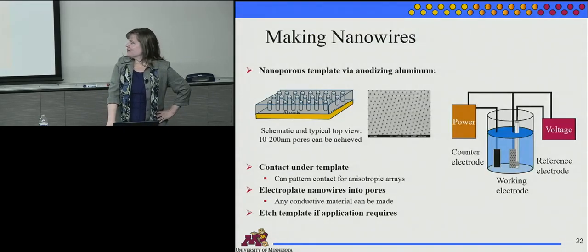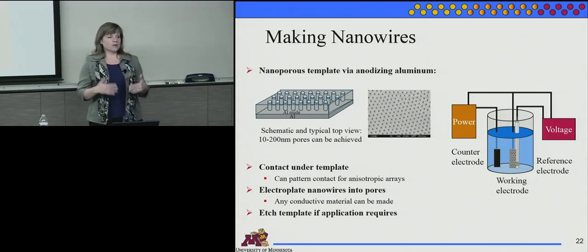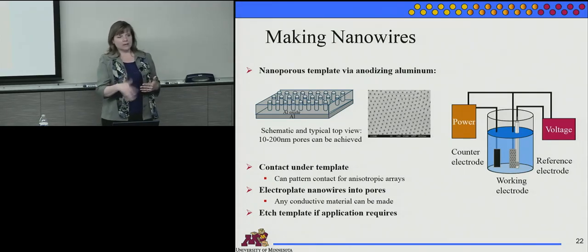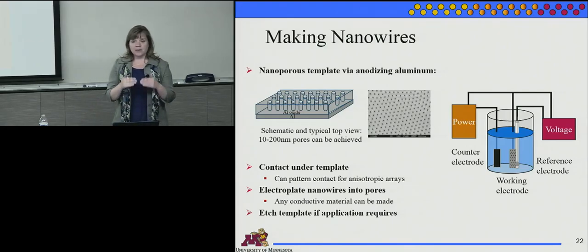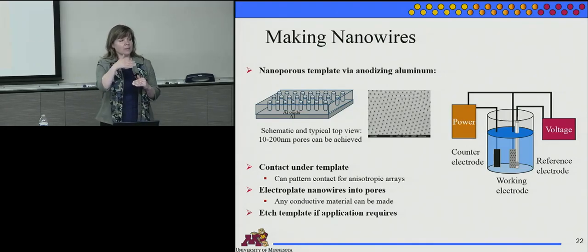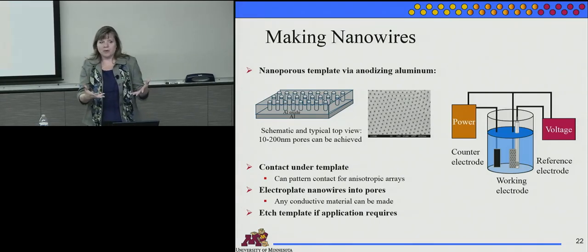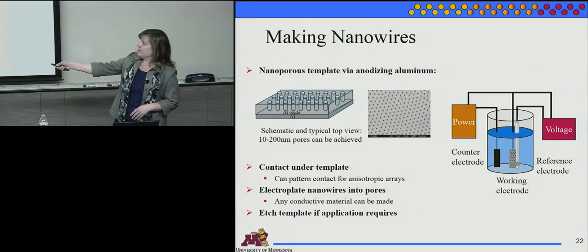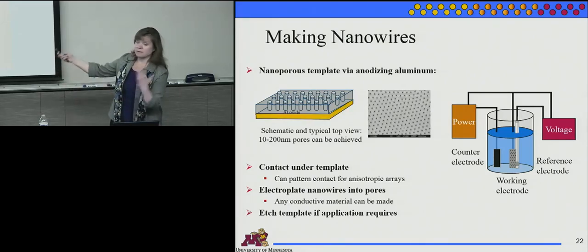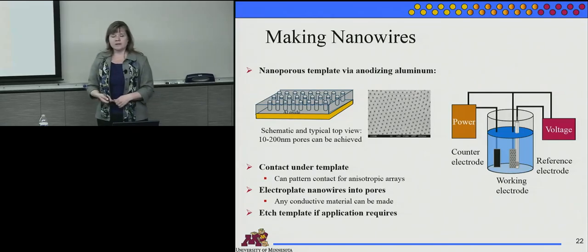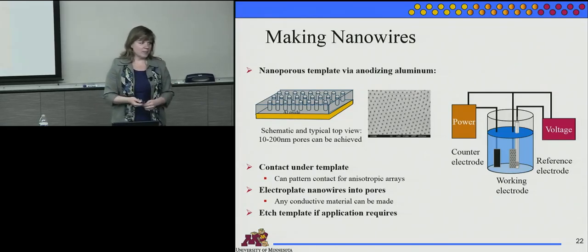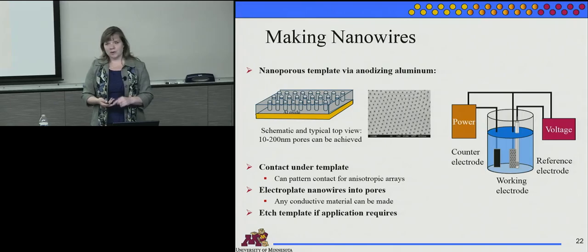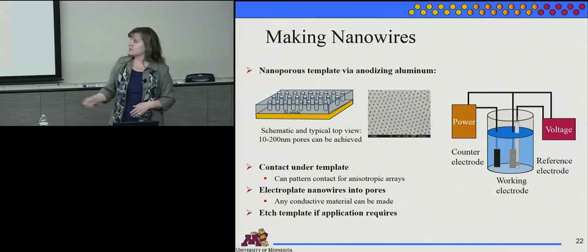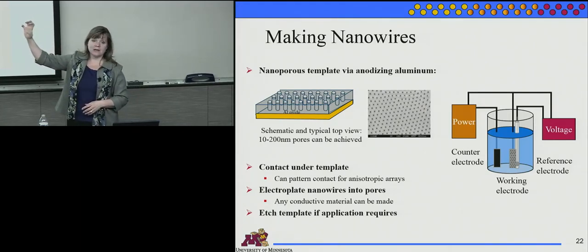So what do they look like when we fill the pores? Well, first is if you're growing on aluminum foil, then you need to get rid of the extra foil you're not using. If you have this sample on silicon and you've deposited copper and then aluminum and anodized, so you use the copper to anodize the aluminum. When you run out of aluminum, you've got pores on copper. Or if you grow on foil and you have to get rid of it and then put some kind of electrode, we've used the normal electrodes, copper, titanium, copper, chromium gold, tungsten gold at times, just different contact materials down here. Now what you want to do is encase that entire thing in polymer.